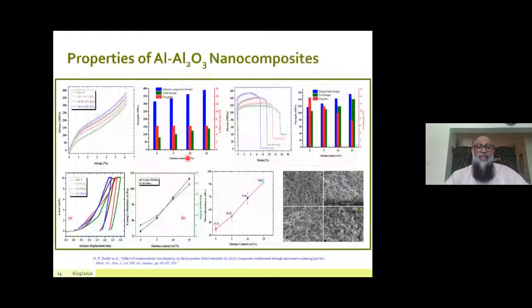Similarly, these are the mechanical properties. We can see that the strength and the yield strength increase with the increase in alumina particles in the matrix, and these are the nanoindentation behavior. Similarly, we can see that the microhardness also increases. The reason is the same, which I have already discussed, because of the dispersion hardening effect and the load bearing capability of the synthesized aluminum metal composites.